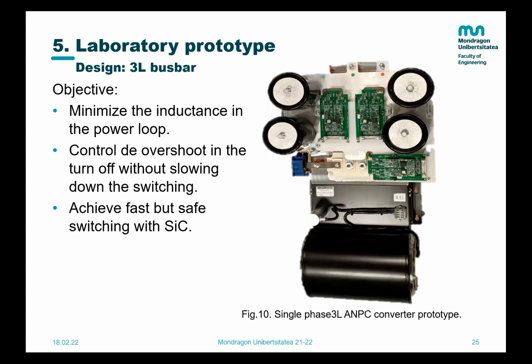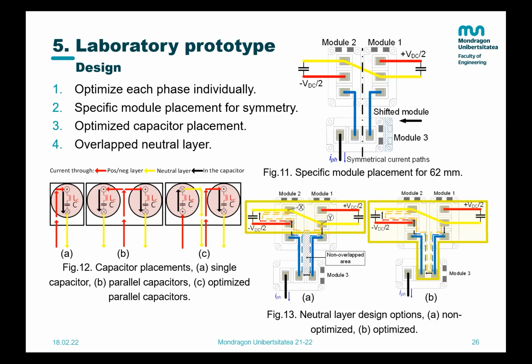Here, I want to highlight a specific design that we did for silicon carbide: the design of the bus bar of the 3-level converter. We did this with the objective of minimizing the inductance of the power loop, so we could switch fast and efficiently, but having the overvoltage under control. To do so, we optimized each phase individually, and we made sure that we had symmetrical current paths by using a specific module placement. As you see here, we shifted the module 3 and we rotated.